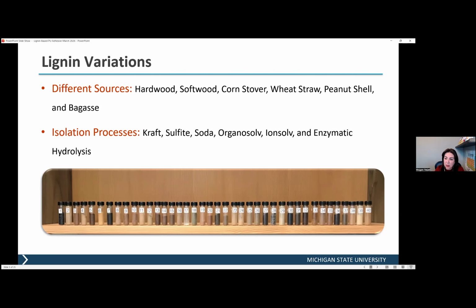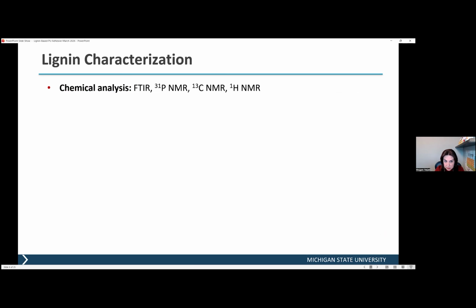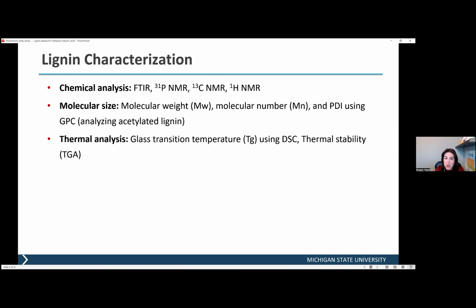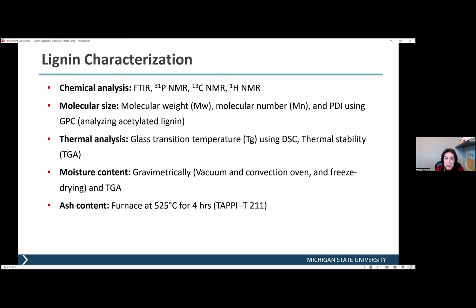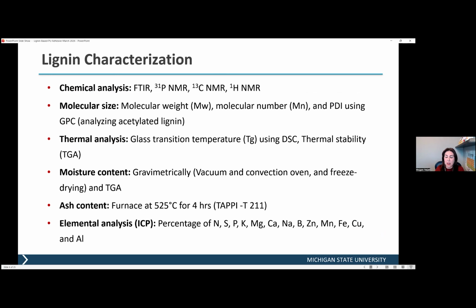These are 40 lignin samples that you can see. They come in different colors. It's not just the color, the properties are different. That's why whenever we receive a lignin sample, we fully measure its chemical, physical, and thermal properties to understand the parameters of the lignin. And based on those properties, we decide this lignin is good for this application or better for this application than other applications.